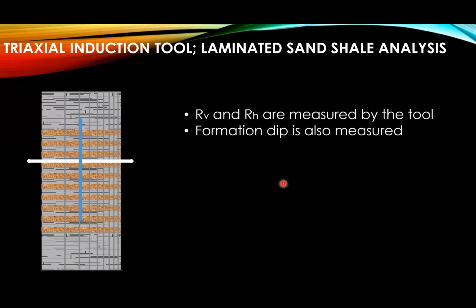Now that we have the vertical resistivity and the horizontal resistivity, we can come up with a resistivity of the sand, Rsand. So now we are unmasking the effect of clay on the resistivity of these individual sand layers, which will now read much higher. And when you estimate hydrocarbon volume from them, you'll have a much better hydrocarbon estimate as compared to what you get with a conventional resistivity measurement.